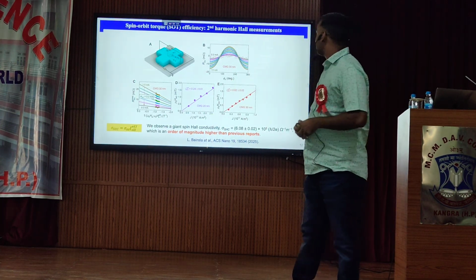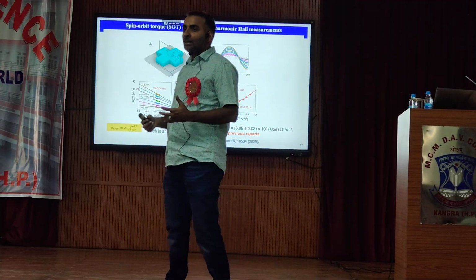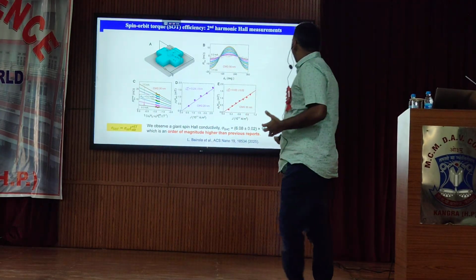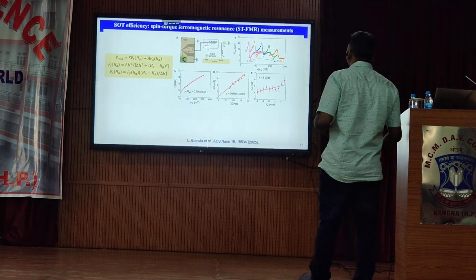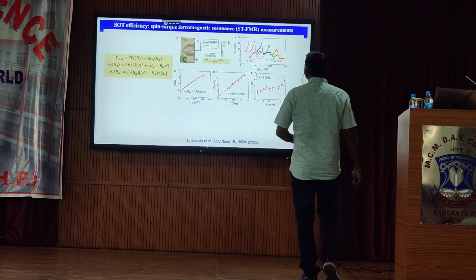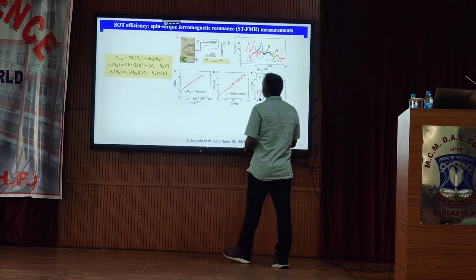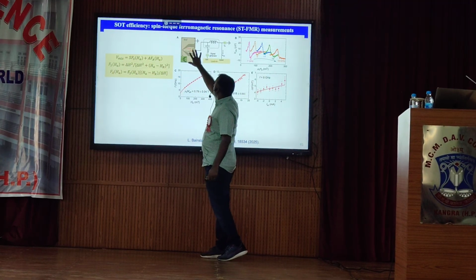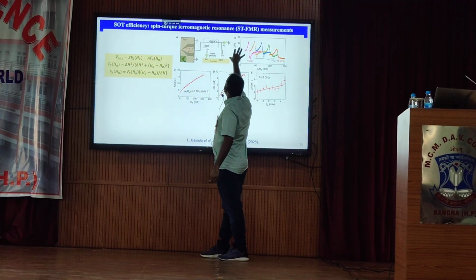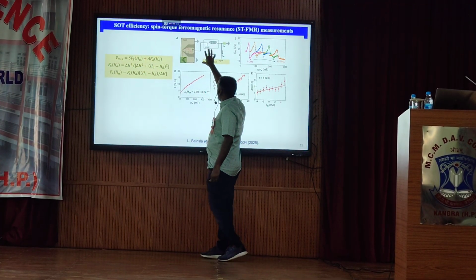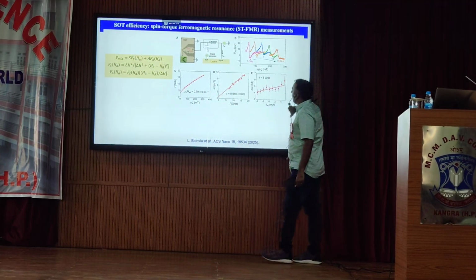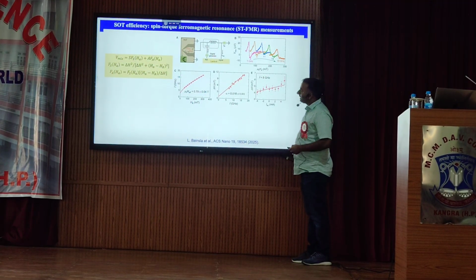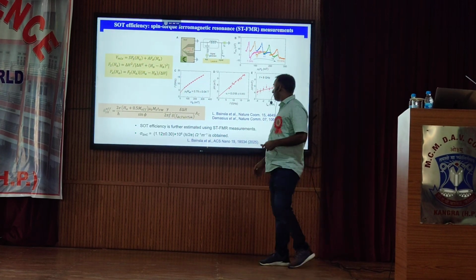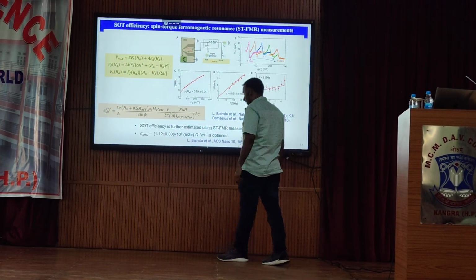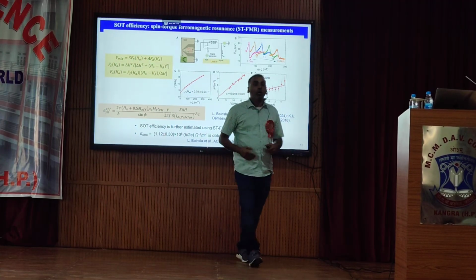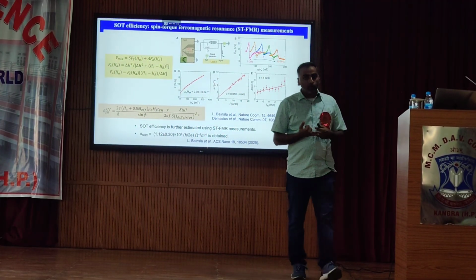We were very excited because we can see the spin orbit torque and magnetism in a single layer. So then we further tried to reproduce the spin orbit torque efficiencies of our material. We then made microstrips here, and the microstrips were used to measure the spin torque ferromagnetic resonance spectrum. The measurement setup is there. Again, I just want to focus on the number, not on the technical details. So using this technique also, we obtain a very high value of spin Hall conductivity, which is reasonably comparable to what we obtained using the first and second harmonics of the Hall measurement.